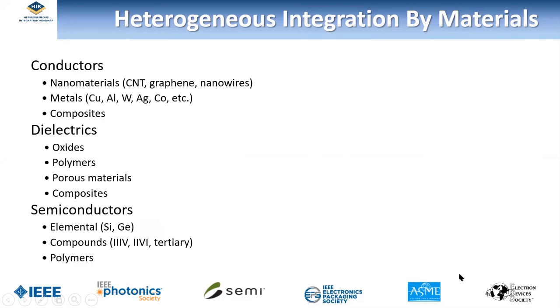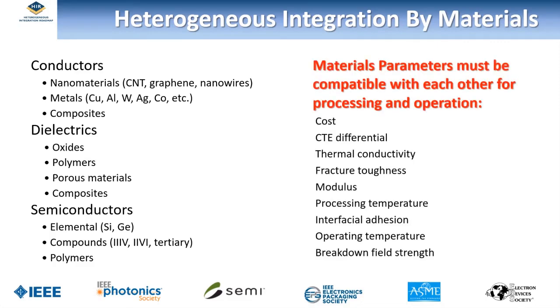And it goes for conductors, where we have nanomaterials and metals and composites; for dielectrics, oxide, polymers, porous materials and composites; and semiconductors, not just elemental. There are 3-5s and 2-6s and tertiary compounds and polymers as well. So the materials parameters for all of these materials have to be compatible with each other for processing and operation, because they have to be compatible with the processing temperatures. And that means that you've got to worry about compatibility from a cost point of view, CTE differential, thermal conductivity, fracture toughness, modulus, processing temperature, interfacial adhesion, operating temperature, and breakdown field strength. So it's not a simple thing to do to make sure that all of those materials fit. They have to be customized.